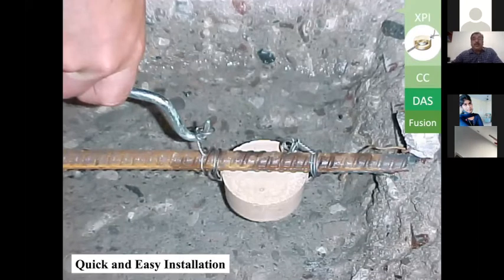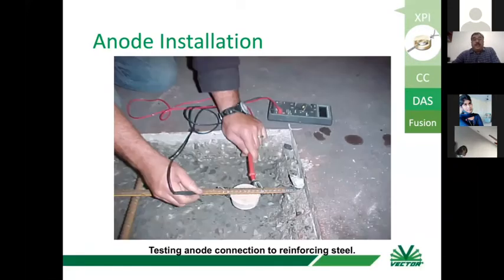After tying, you check the connectivity, whether it is properly connected to the steel. At the connection, the steel should be cleaned properly and there should not be any coating over the steel. This has to be ensured, otherwise this anode will not function. I have seen various cases where the anodes were loosely connected or lying outside. You can see the anode is inside the concrete cover, with proper cover over the anode so that ionic movement can happen from the cover part, and the steel is properly connected so the anode will function.